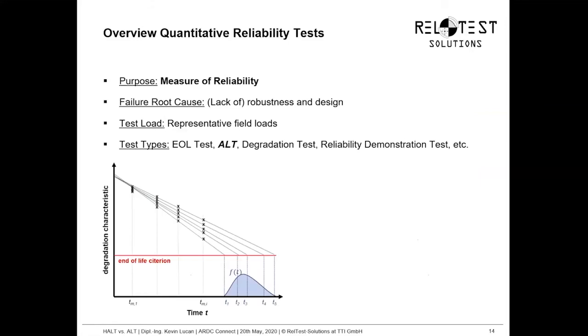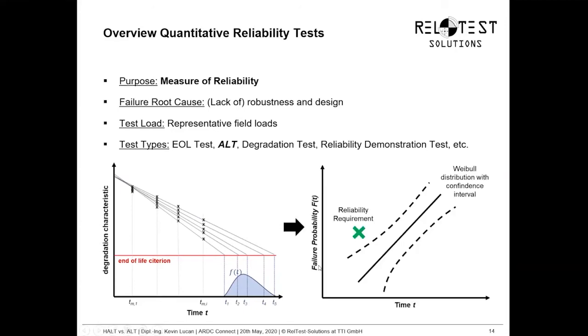In a degradation test, we measure our degradation characteristic over time, then we estimate our degradation model. We make a prognosis for when the end-of-life criterion is reached, and then we can make a classical life data analysis to measure the reliability of our product and, for example, to demonstrate the reliability requirement. So demonstrating a reliability requirement is a classical purpose of a quantitative reliability test.